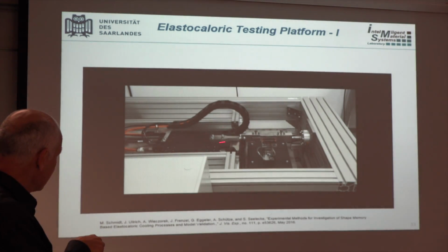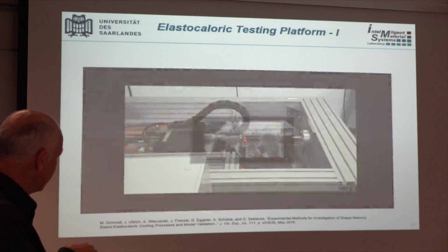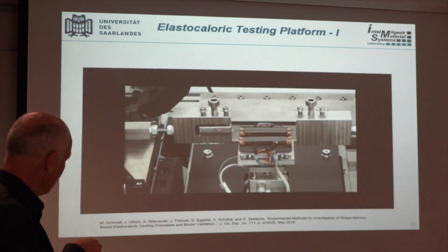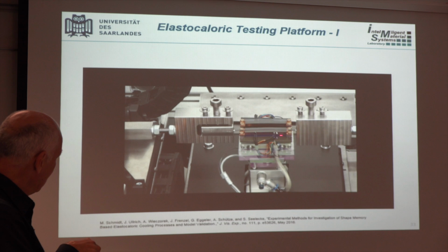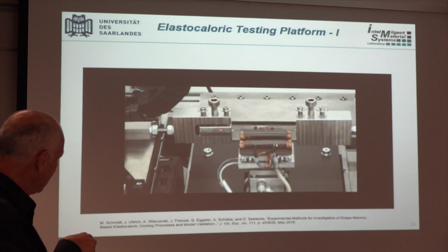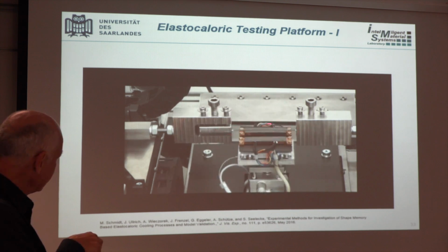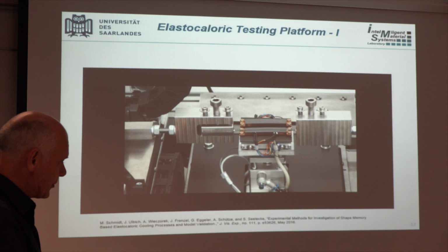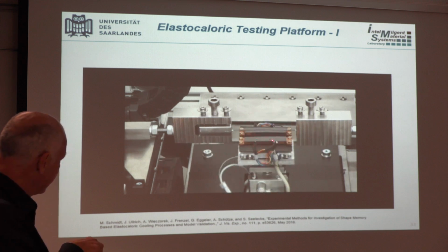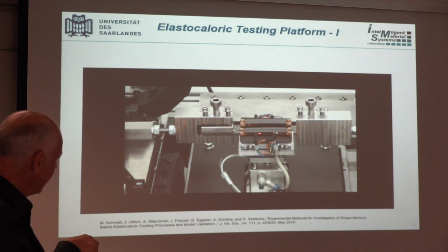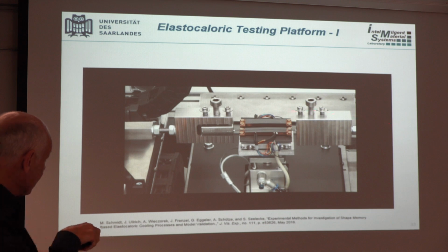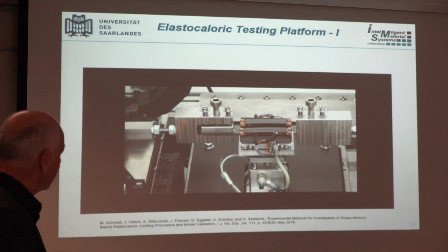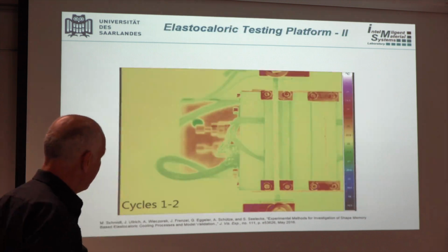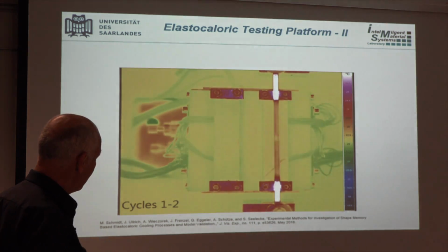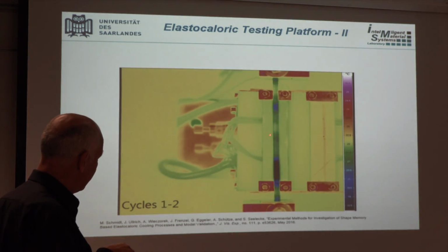So first thing in here is we built an experimental testing setup to do exactly what I just described. We stretch the wire where it changes from austenite to martensite, and when we unload, it changes back and absorbs heat. And when it absorbs heat, it takes heat off the heat source, and then upon stretching, we give it off at the heat sink. So this is the mechanics. Here's the thermal image picture of the same process, right?